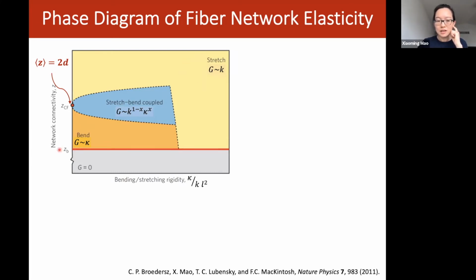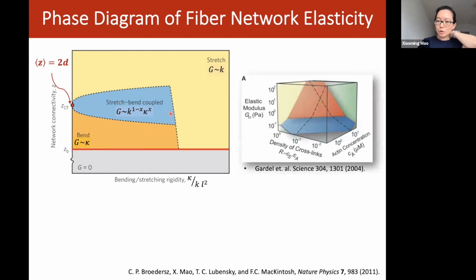And then this is the connectivity percolation point. Below that, the network is not connected, so of course it doesn't have elasticity. And in the middle, because of this critical point, you have a regime where stretching and bending are coupled and the elastic modulus depends on both. So this qualitatively explains why in many materials the elastic modulus can change by orders of magnitude as you change these geometric parameters, because it comes from a crossover from bending dominated behavior to stretching dominated behavior, where the stiffness is very different.